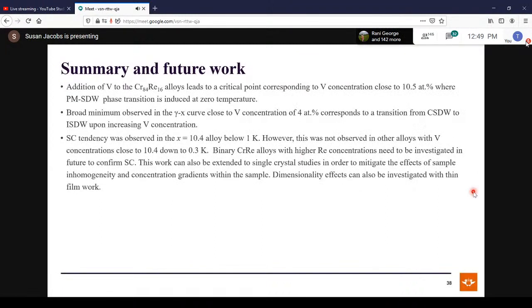So the conclusion from this work is that in the chromium-rhenium-vanadium alloy system, we saw that there is a critical point at about 10.5 atomic percent vanadium. The minimum in the Sommerfeld coefficient curve corresponds to the transition from the commensurate to the incommensurate spin density wave phase. Superconducting tendency was observed in the 10.4 alloy below 1 Kelvin, but we could not observe it in other alloys close to this concentration.